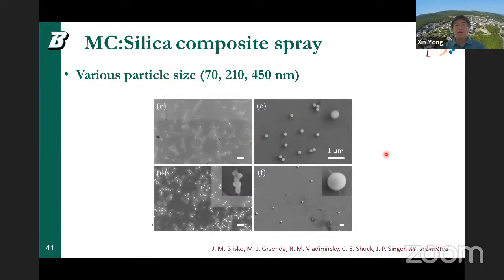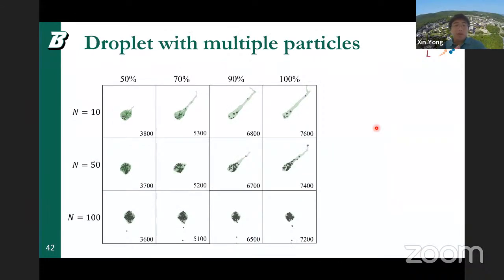We also realized this by spraying a methylcellulose-silica composite. As you can see here, we observe a very similar tiny filament if the particles are very large. So it basically occupies the entire droplet's volume. But for small particles, they can be well dispersed in the small nanowire. And then what happens if we introduce multiple particles that have very small size? In this case, the solid fraction is increased, but they are fairly homogeneous compared to individual big particles. And so we see here that we can also suppress the deformation when the solid fraction is high, but when the solid fraction is low, we observe a more robust nanowire formation.